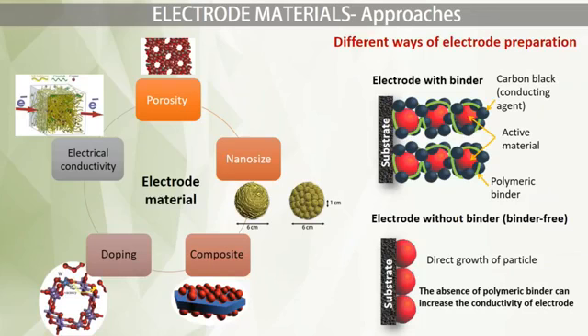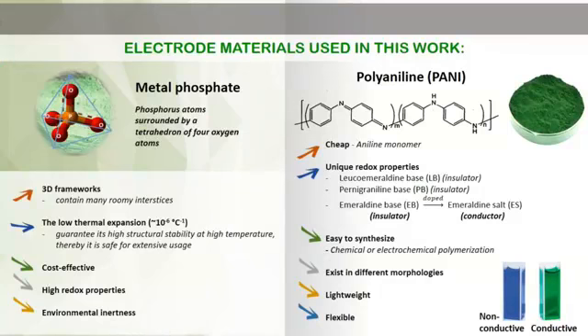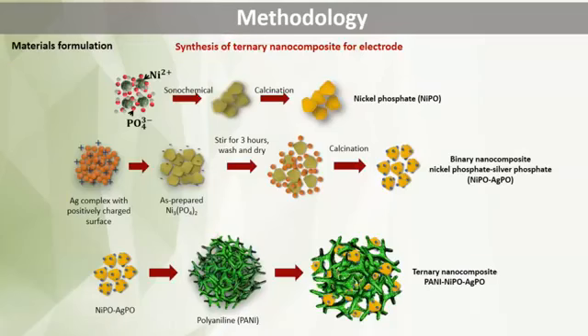So now we are focusing on the electrode without binder. The absence of polymeric binder can increase the conductivity of the electrode. So we use metal phosphate, which has a 3D framework with a low thermal expansion, as a core material. And we are also using polyaniline as the electrode material because polyaniline has unique redox properties whereby, with appropriate doping, they can change from insulator to become a conductor. Okay, these are material formulations.